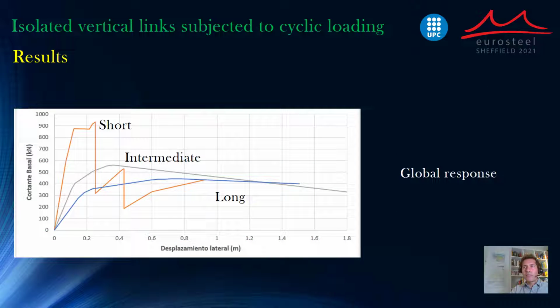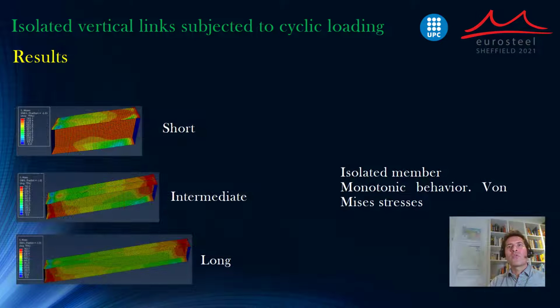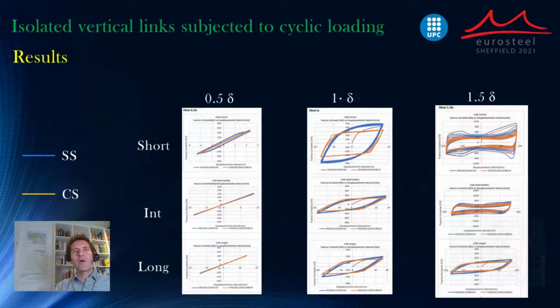For the case of the global response, we can see here in the slide that the short, long, or intermediate elements provide different stiffness, different strength. This is expected. Okay. When it comes to results on isolated members subjected to a monotonic loading, you can see von Mises stresses in which we can also see the corresponding shear-like or bending-like failure mode.